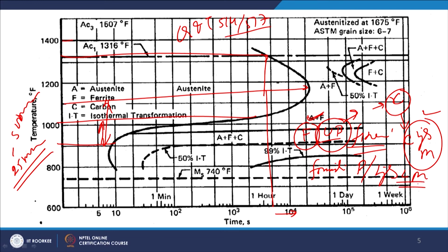So, the formation of soft and hard phases will be leading to a lot of heterogeneity in the structure as well as mechanical properties, and such phases lead to the reduction in the notch toughness of the steel. So, when the steel is exposed at further lower temperatures like below 950 degree centigrade, the transformation occurs very quickly. It takes a very short time to transform. That is what we can see from this diagram.